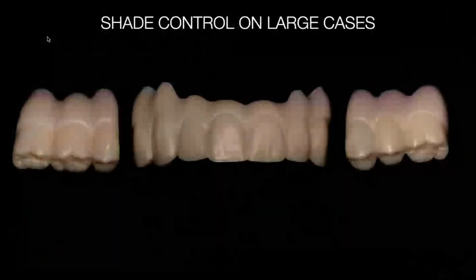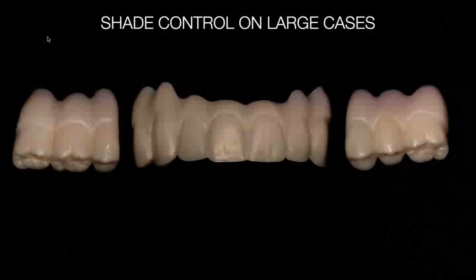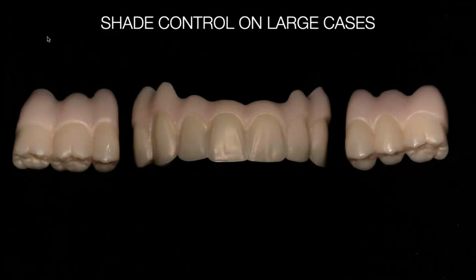is, here's one that I did 4 or 5 years ago on a white zirconia. This is a full upper in 3 pieces on an implant case. And then I have very, very little room for porcelain, but I just have enough. And then I put the pink material on top, the gingival material. At that time, this was my first case with Lumex, which has a low fusing gingival porcelain. And the reason I like the Lumex material on zirconia is that it only fires to like 760, 770. So it doesn't burn out the color of the pigments in the zirconia.